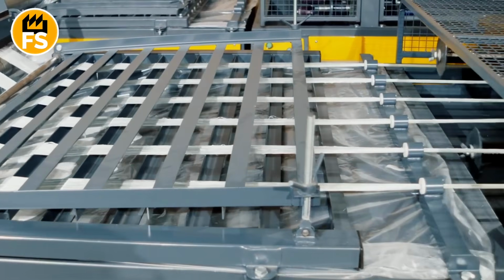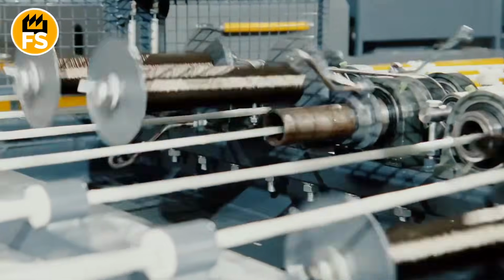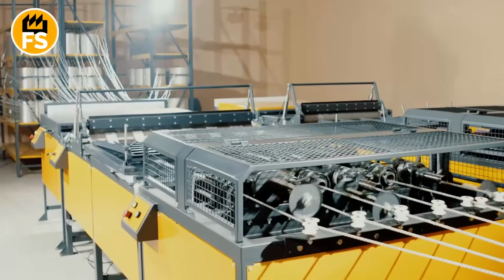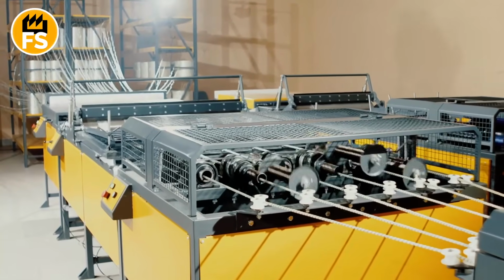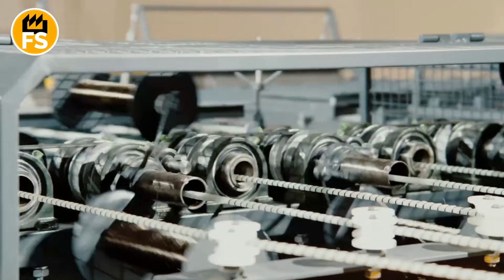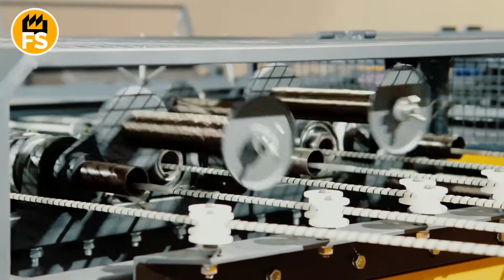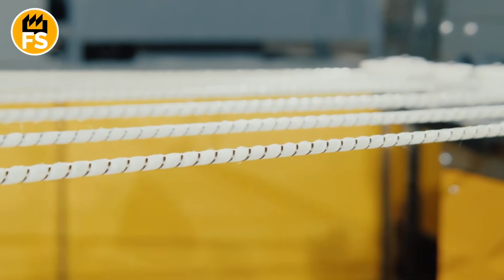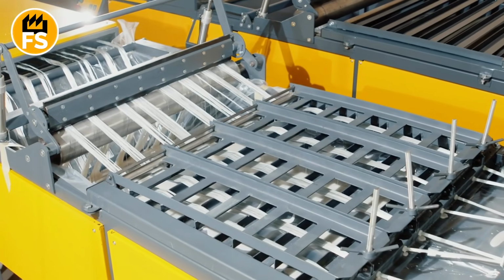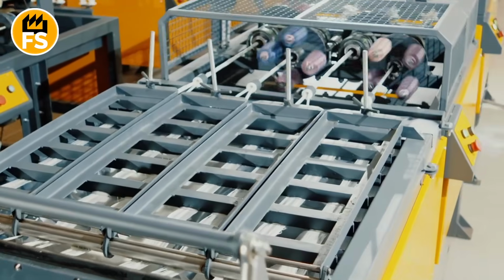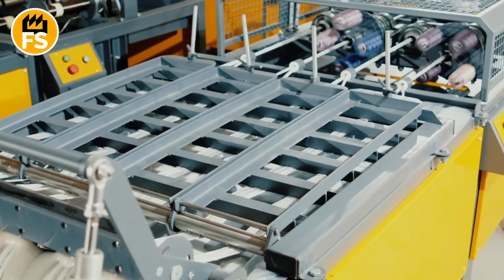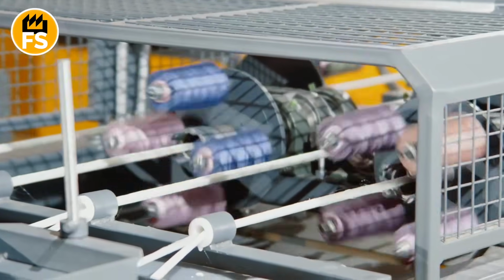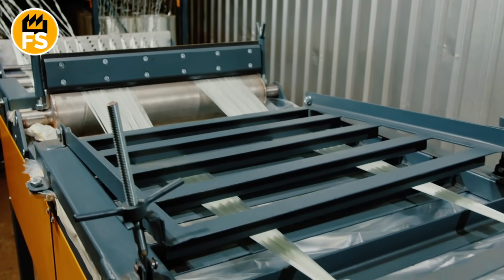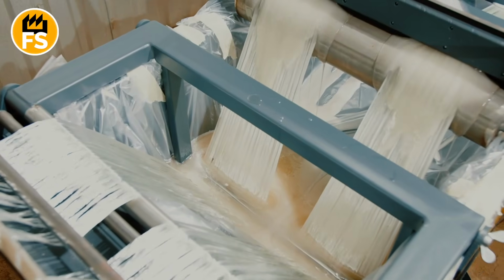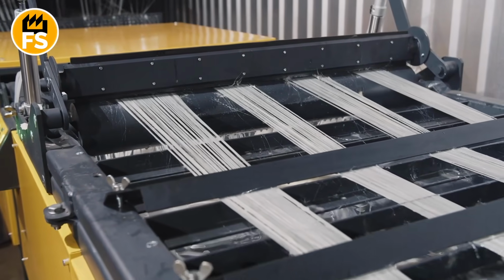the forming die. This is the heart of the whole process. Imagine a thick steel plate with a perfectly round, polished hole, the diameter of which exactly corresponds to the diameter of the future rod. The die is heated to a certain temperature. When the wet bundle is drawn into this hole, several things happen at once. First, the die, like a press, squeezes out all the excess resin, leaving only the necessary amount.